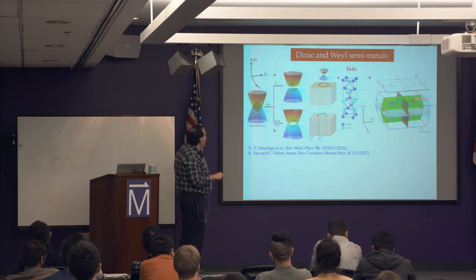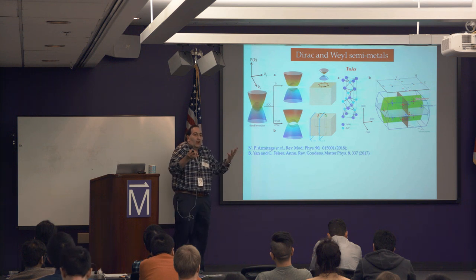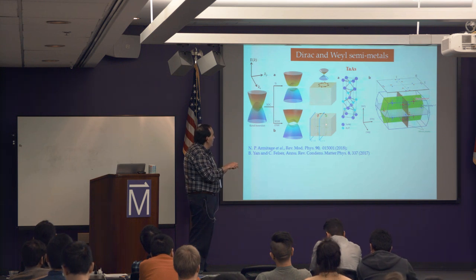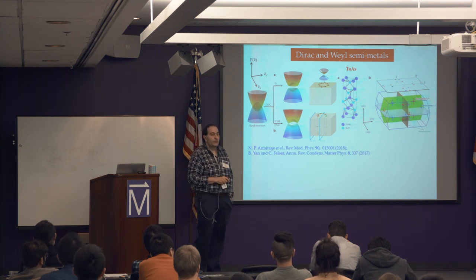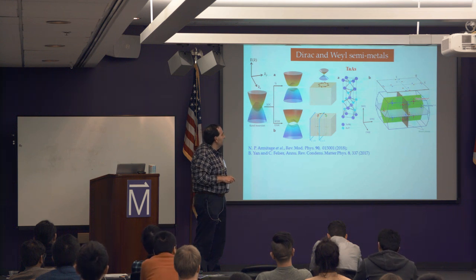And again, as we discussed, if you create a surface around here, you get these so-called topological charges, by analogy with the electrostatic charge that you would get with a real charge. And the projections, we already said, since you have a Chern number, we said we should have a surface state, and you do have these Fermi arcs. You project your Weyl points from the bulk to the surface, and they connect these surfaces. So in tantalum arsenide, there are twelve pairs of Weyl points. Blue and red define the topological charges, and as you can see, there are different separations, Weyl 1 and Weyl 2, some of them at Kz equals 0, and the other ones in a different plane.